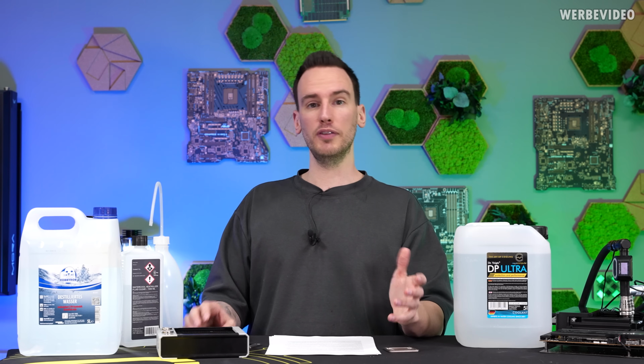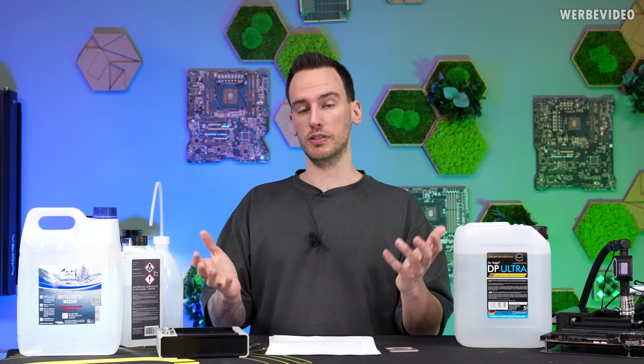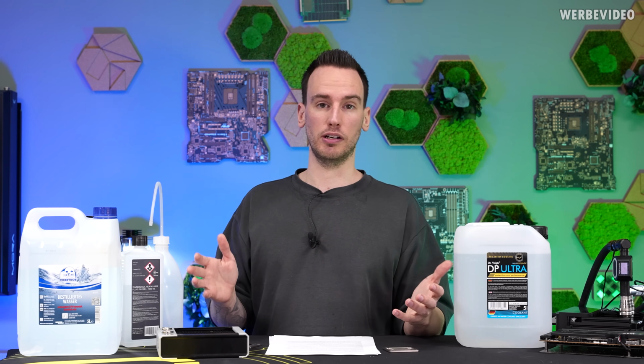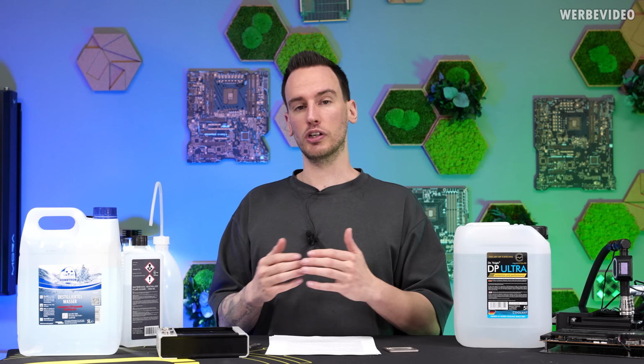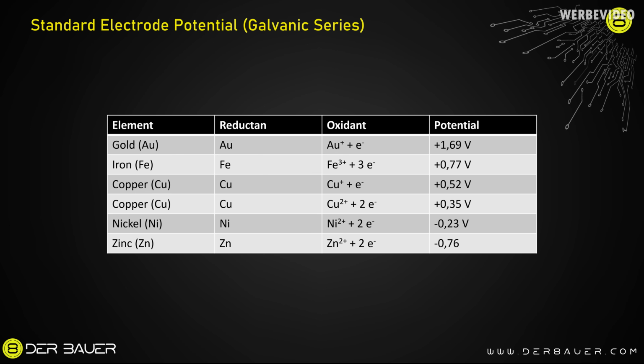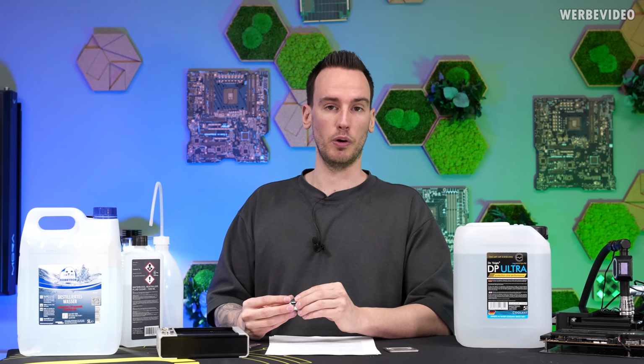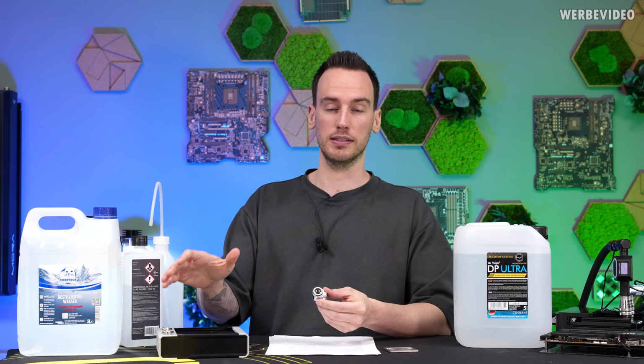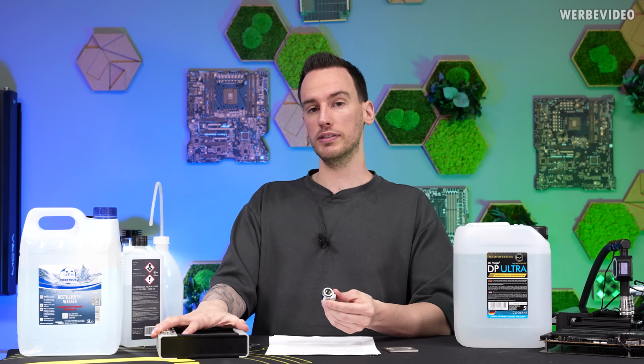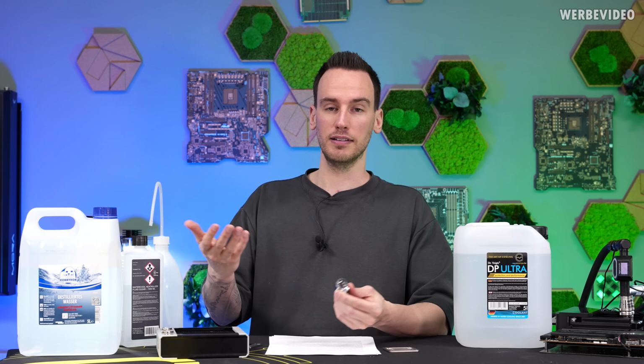This can be a much bigger problem if you take a look at your entire loop, and also what we discussed earlier with the broad range of materials that are being used, because in the galvanic series, the copper and the nickel are fairly close to each other, so it's not that much of a problem. But then, for example, we have the zinc inside, which is part of the brass, and brass is much lower, so it's much more of a base material, not as noble, which definitely causes more corrosion than you might think. And that is definitely happening if you're adding distilled water and you use brass fittings, for example, you have brass inside your radiator, then it will cause discoloration, for example, of your nickel plated GPU heatsink.